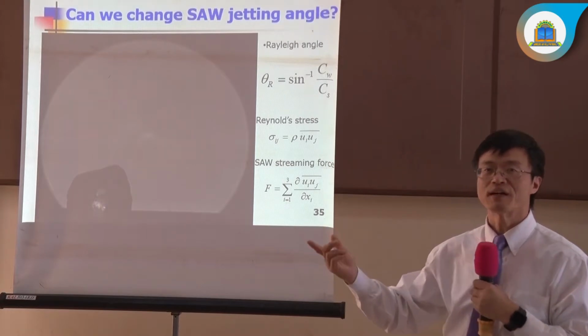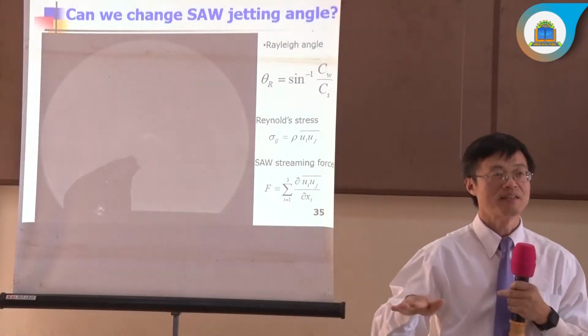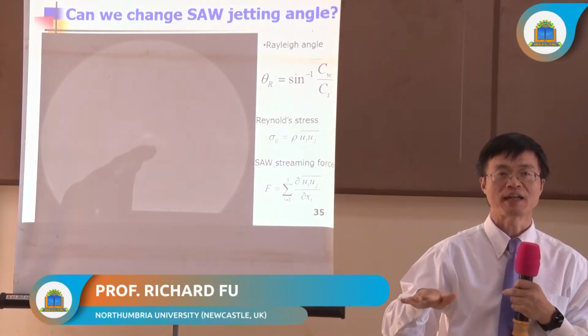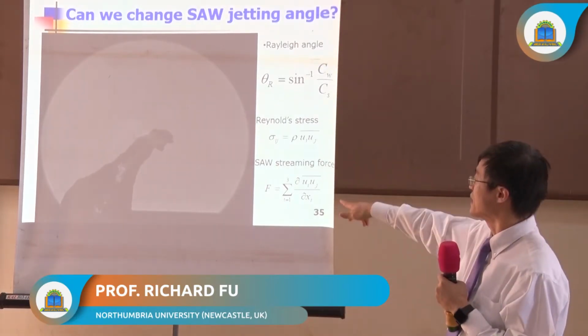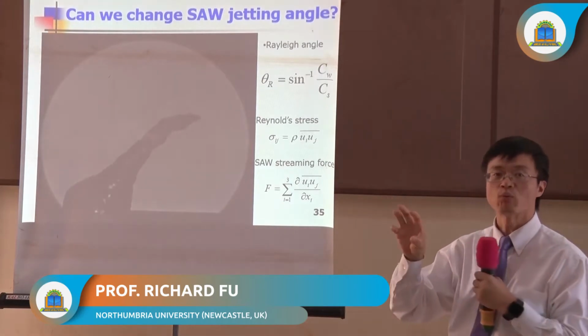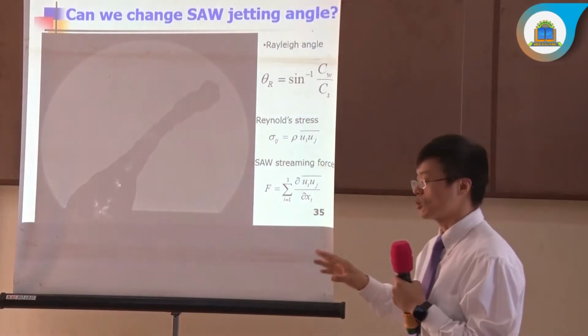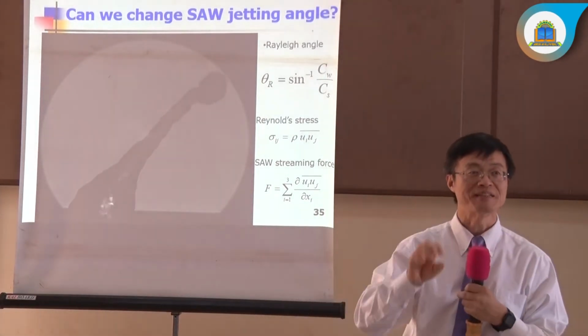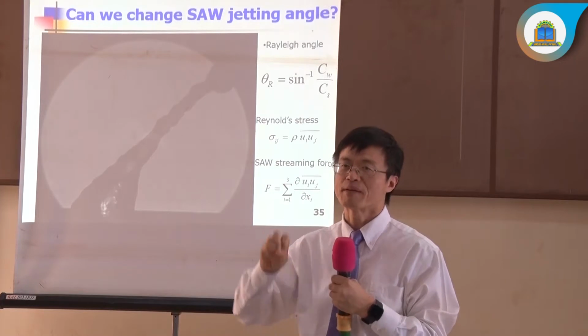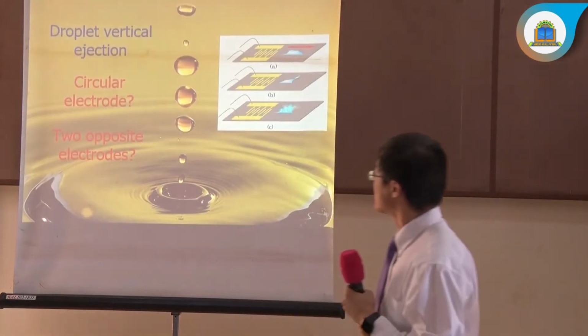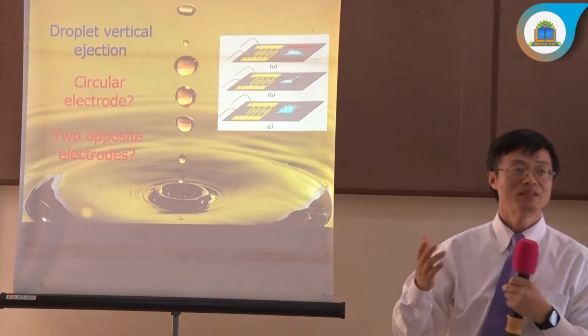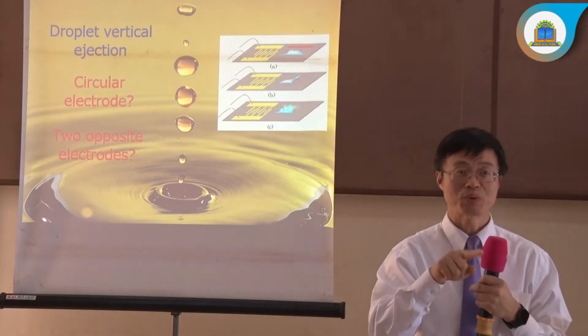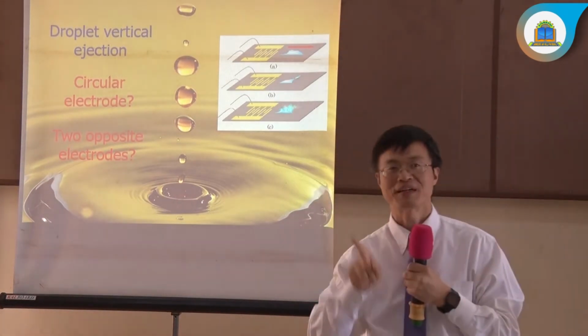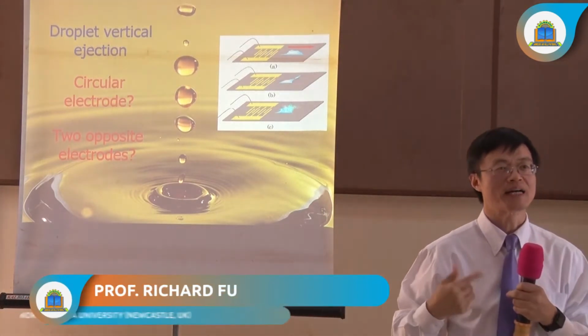This is on a very standard aluminum substrate. You can deposit the piezoelectric film on any substrate, like an aluminum plate. Then you can see that there is a significant wave propagation in the liquid and significant ejection of liquid. So we claim that, oh, this can be used for printing, right? We can eject the droplet, printing on paper. But the trouble is that for printing, we need vertical jetting, right? Nobody wants this angle, that angle, right? So how can we realize the vertical jetting?